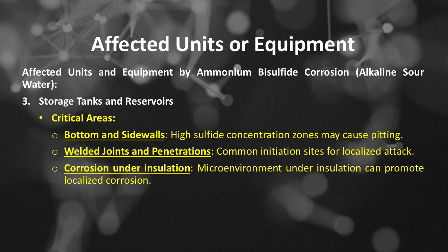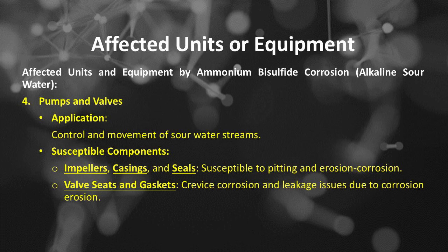High sulfide concentration zones may cause pitting. Welded joints and penetrations are common initiation sites for localized attack. Corrosion under insulation: the microenvironment under insulation can promote localized corrosion. Affected units and equipment by ammonium bisulfide corrosion or alkaline sour water. Number 4 is pumps and valves.